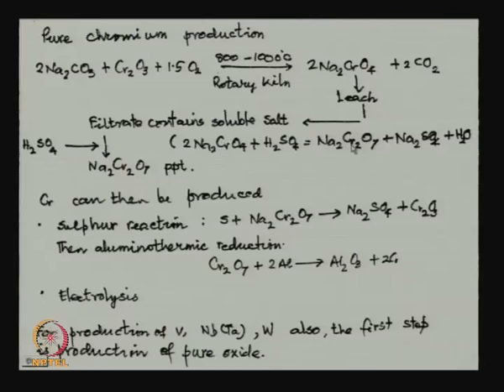2Na2CrO4 plus H2SO4 will give Na2Cr2O7. This will be in solution. Now, once you get a precipitate, which is a very pure compound of chromium, chromium can be produced in many ways. It can be made to react with sulfur to produce pure Cr2O3. Then we go for aluminothermic reduction to produce pure chromium, or Cr2O3 can be dissolved in a suitable electrolyte and we can go for electrolysis. Actually, for production of any of these ferroalloying elements in elemental form, we have to start with the pure oxide.